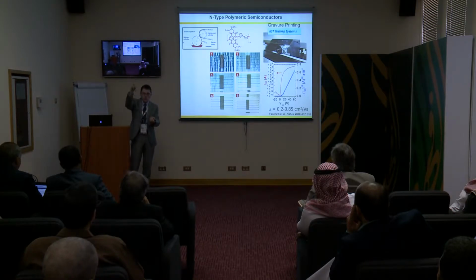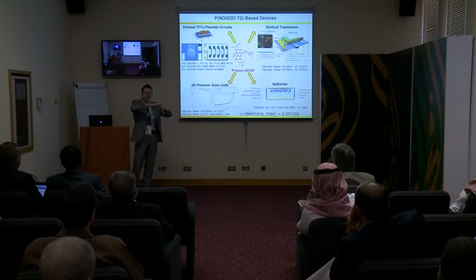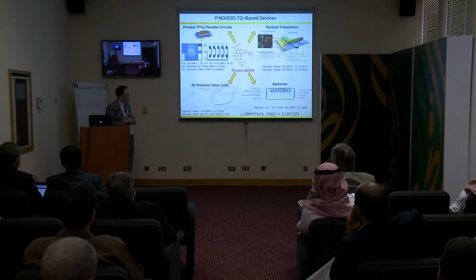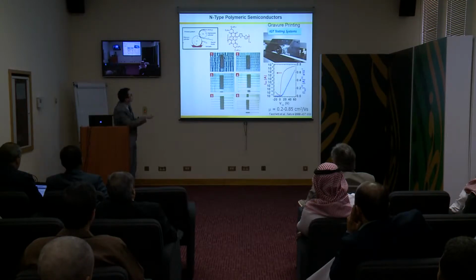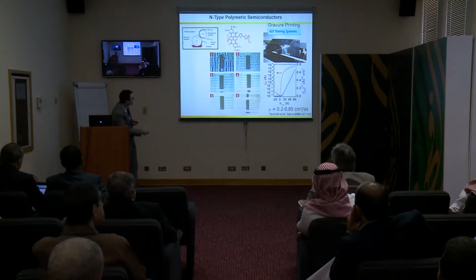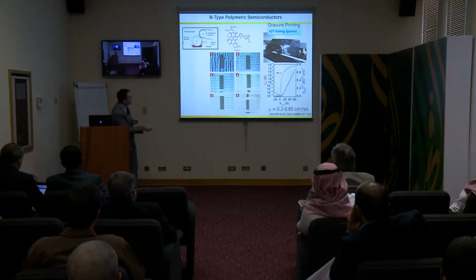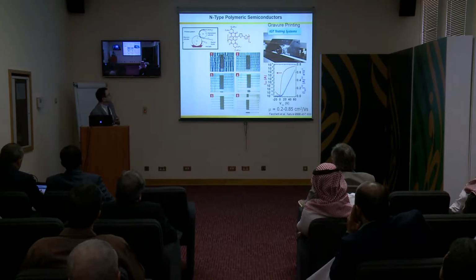It's not like a drop which is ejected on your substrate. You have a sort of cups, and these cups you just like a cake, you just dump on your substrate, and then they melt together, and they get closed. So using this particular polymer, which we developed a few years back as an n-type conducting polymer, by tuning the viscosity of the solution we could get films which are uniform enough, thin enough, continuous enough to make quite nice field effect devices fabricated by gravure printing, which is a more mass producible technique.